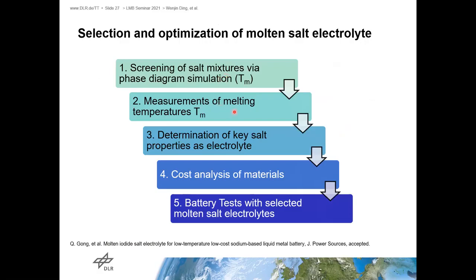Then after that, use a method to measure the melting temperature. After that, use experiment or simulation to determine the key salt properties as electrolytes. Then do the cost analysis of the materials. And after that, use the battery to test the selected molten salt electrolytes. Maybe it can also do several cycles to get to the optimal salt mixtures as electrolytes, and also the optimal battery performance.